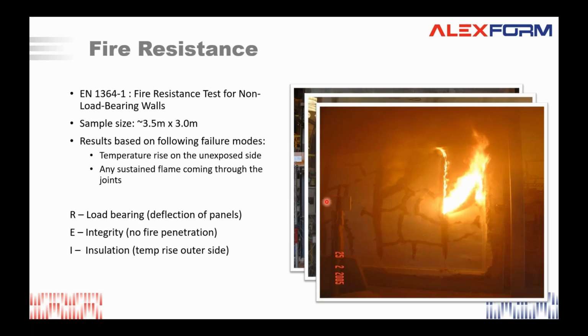With PIR panels, with 200 millimeter thickness, you can achieve 2 hours of resistance. And this is more than enough for, I would say, 90% of the projects, which should give you an idea about the comparable performance of PIR foam versus mineral wool panels, basically.